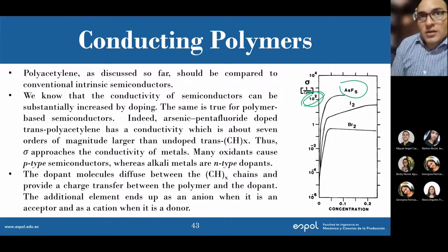Whereas, you know, in a semiconductor, you dope with 0.01% or 0.12% at maximum, right? So it's very small additions. Whereas here, doping means a lot, around 20 to 40% of dopant. Okay, is it clear so far?